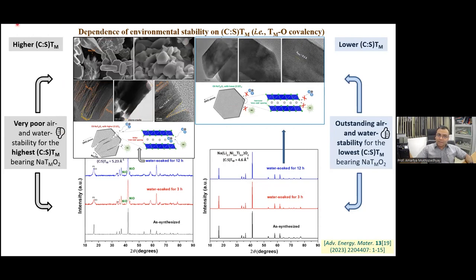Now, when we looked at the water soaked materials in TEM, we can see that this material having the highest charge to size ratio in the transition metal slab, and which has the highest covalency, and hence the weakest sodium oxygen bond, is highly susceptible to damage upon exposure to water. However, this material is highly stable even upon exposure to water for up to 12 hours. There is no change in structure that one can see even with high resolution TEM.